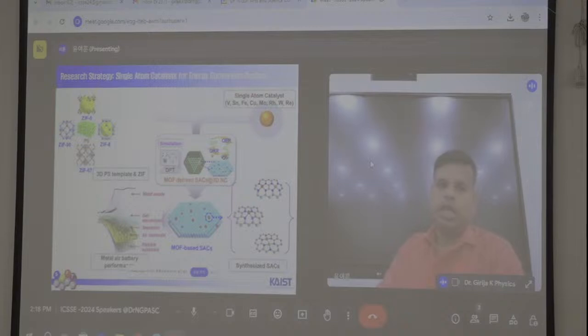You can see in our studies, we first fabricated a MOF-based material. Why are people moving to MOF-based material compared to other materials? MOF-based material has a high surface area. Therefore, we have chosen a MOF-based material as a templating agent to get single atoms decorated on the carbon support material. Especially MOF-based material has highly porous networks, so we fabricate highly porous networks to let electrolytes penetrate, and the ion transportation and kinetics will be enhanced. So in order to avoid the kinetics issue, people are going for porous material with single atom catalysts.